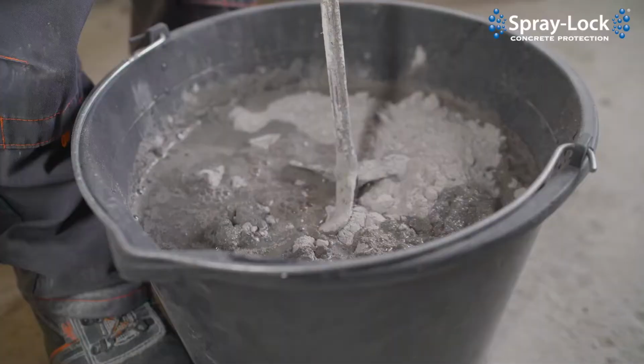And for years, before we really started getting into the chemical admixtures and pozzolans, the supplementary cementitious materials that we have today, the water to cementitious ratio you needed to get strength would also provide durability. Right. And since about the 1970s or so, we've really improved the way we can gain strength at early ages. We're able to use less cementitious material and more water, and still get the strengths we're looking for.